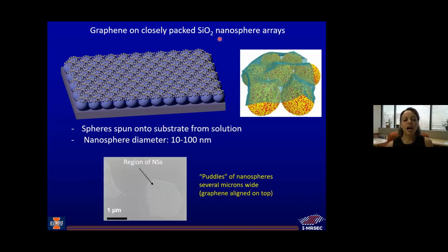Okay. And this is an optical image of what happens when we spin these nanospheres onto our substrates. So when we spin them on, we get these puddles of nanospheres that are several microns wide. And then to do lithography, we align the graphene on top. And so we transfer a sheet of graphene, and then we figure out where it's on top of the nanospheres and then etch away everything but the graphene on top of the nanospheres plus some control samples.